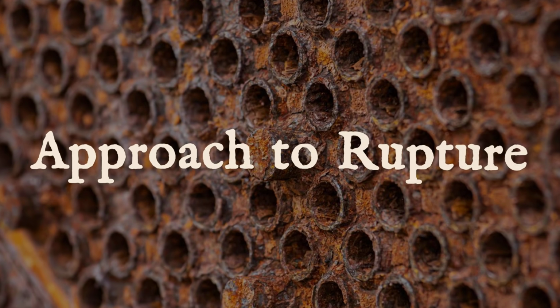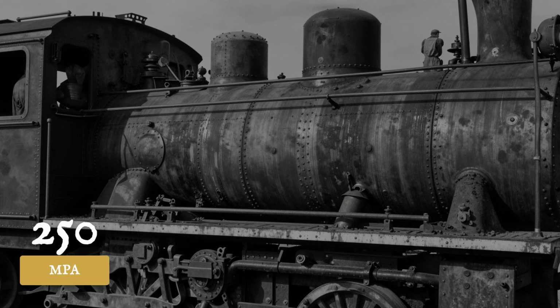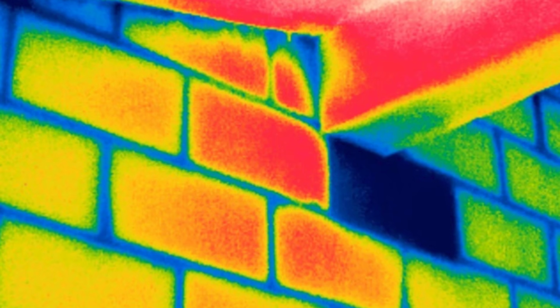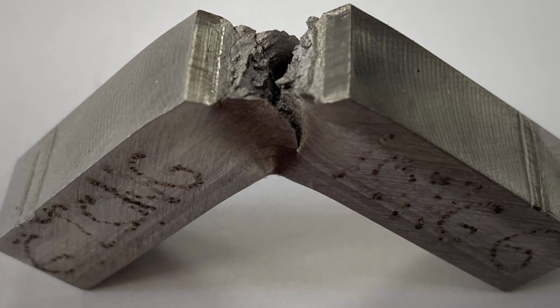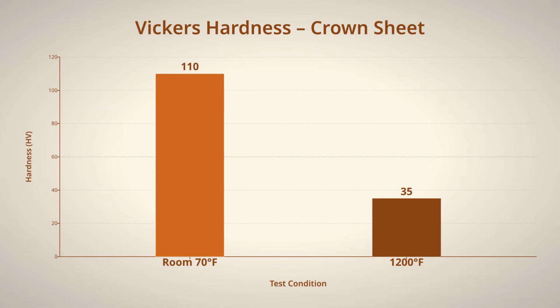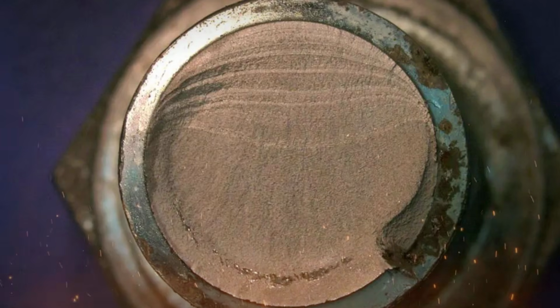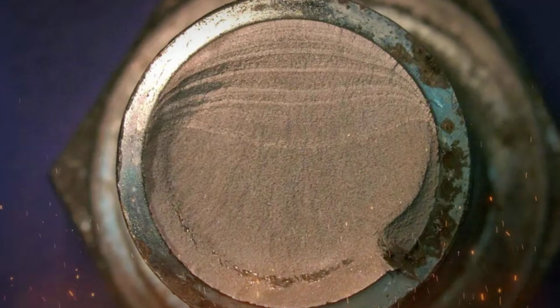Steel remembers every degree. A crown sheet that once held firm at 250 megapascals turns to butter at 550 degrees Celsius. The microstructure changes, grains coarsen, pearlite breaks down, the toughness drops like a stone. Lab reports show Vickers hardness falling from 110 at room temperature to 35 at 1,200 degrees Fahrenheit. That is not a margin, that is a death sentence signed in heat.